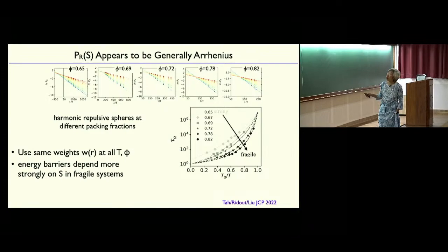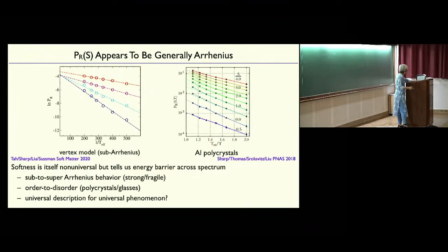But you see that for all of these different densities, again, the log of the probability of rearranging versus 1/temperature is Arrhenius for a given softness, for all of these different systems. Here, we're using the same hyperplane for all of the different temperatures and all of the different densities, so we can compare them next to each other. Same definition of softness for all of them.